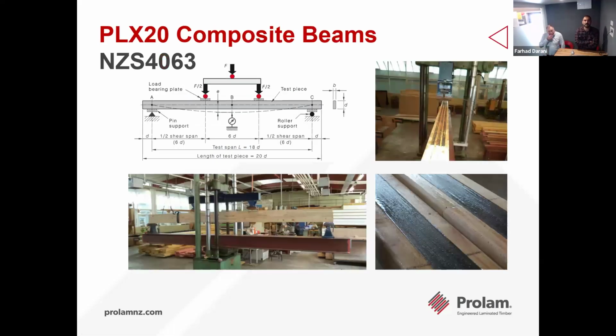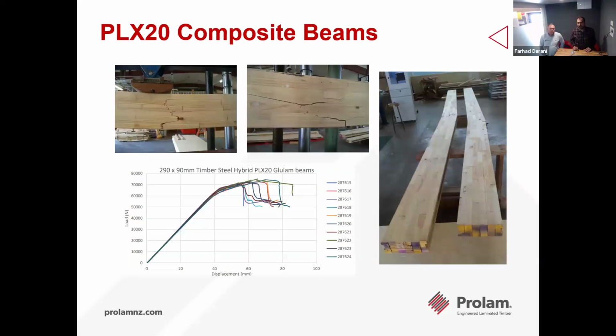So also 4-point bending tests based on NZS 4063. So just to measure the stiffness and the deflections. So you can see here we have tested two different variations. One is with 3 steel rods actually inserted and epoxy to the top of the beam, and then this is just a simple rectangular steel bar. So after these tests, actually we decided to go ahead with the rectangular section only, and then we did some strength tests as well.